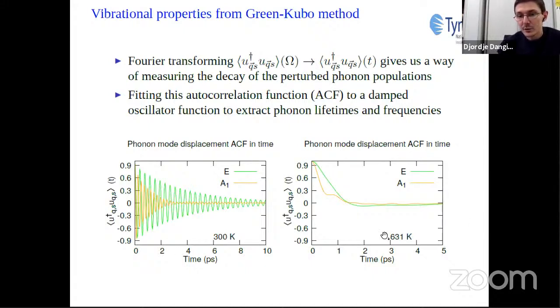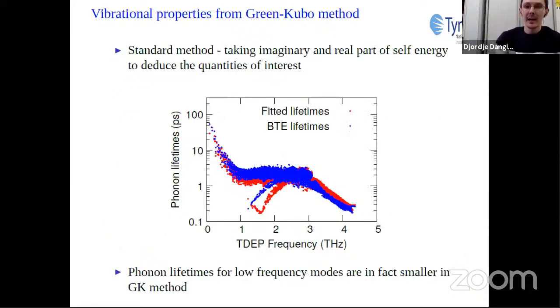We can fit these two behaviors to the damped oscillator function to extract what we usually associate with phonon lifetimes and frequencies. If we do that and we plot the fitted lifetimes as the red points here and the Boltzmann transport equation lifetimes as the blue points, we can see that the fitted lifetimes are indeed smaller than the Boltzmann transport equation lifetimes, which is in accordance with the spectral function graph.